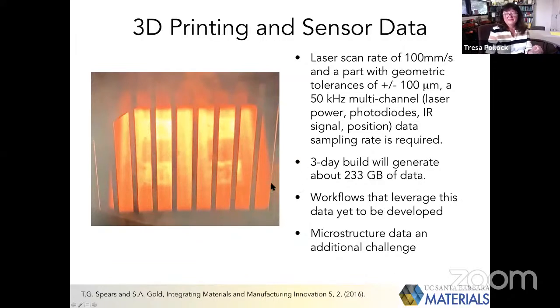Now I'm talking about the data that we have at the melt pool scale, and we all know that that's a very small volume compared to the total volume. And so from the point of view of future challenges for additive manufacturing, data is certainly high up on the list. If you imagine that you're building a part and basically gathering image information, and that the build is 3 days long, you're likely to generate something like 230 gigabytes of data. And so bringing this sort of data into the melt pool scale is yet another challenge. And so there are many things for those of you who graduate and work on this in the future to do.